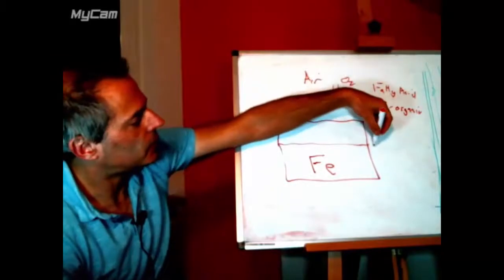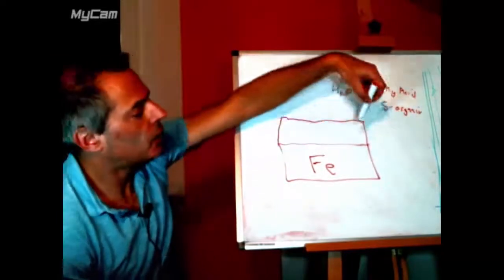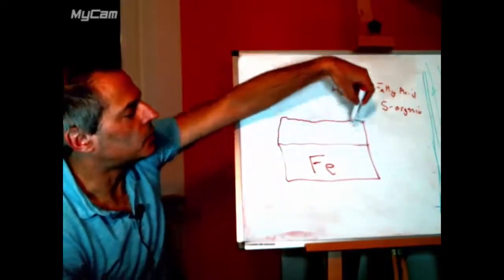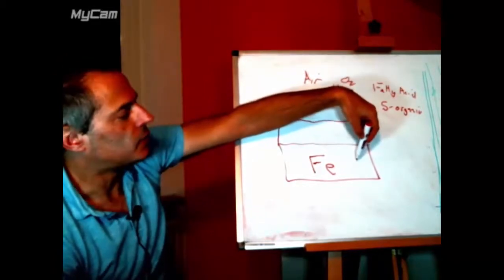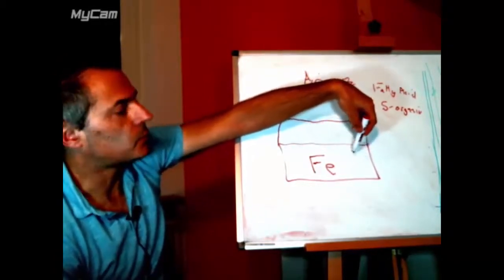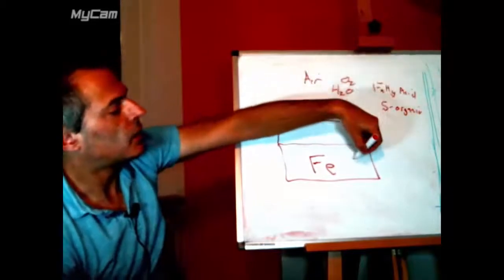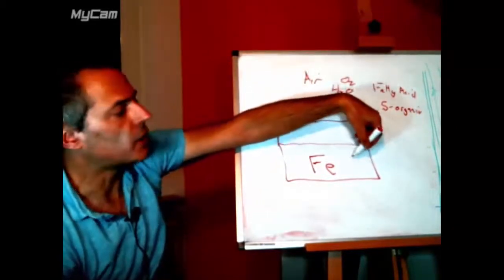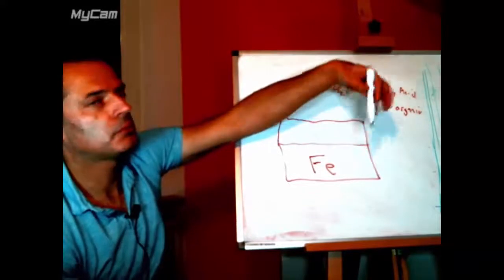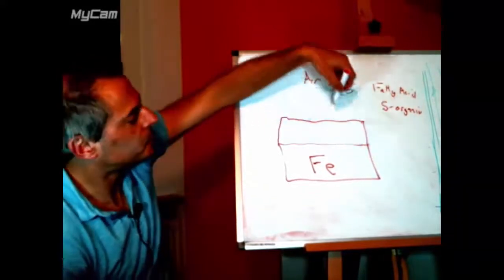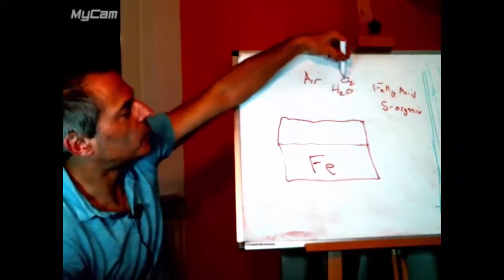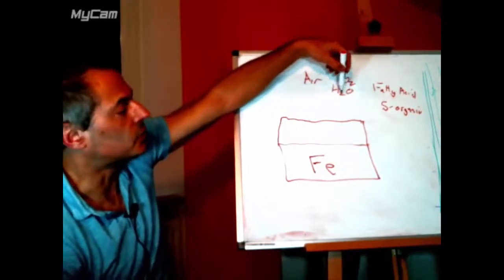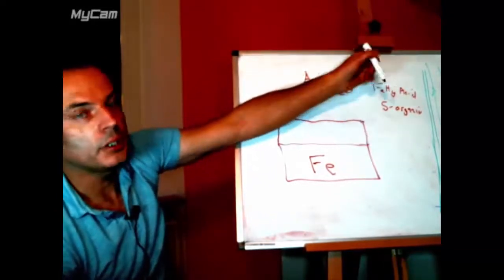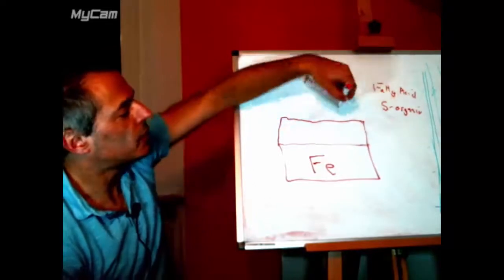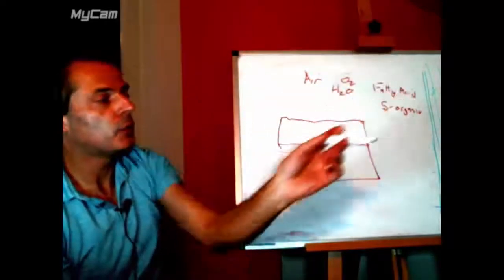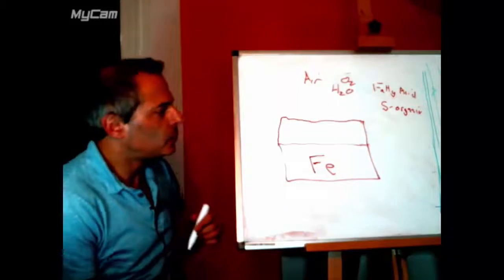So our previous topic would be corrosion, and if we're going to corrode this iron, there would be a change in the electrochemical potential between the iron, which is at the electrochemical potential of iron turning into iron 2+, because it's already iron 0. And on the outside, we've got the electrochemical potential of the oxygen. And so there's got to be some kind of way of getting from one to the other, and that's this oxide layer, which in iron is quite complicated because